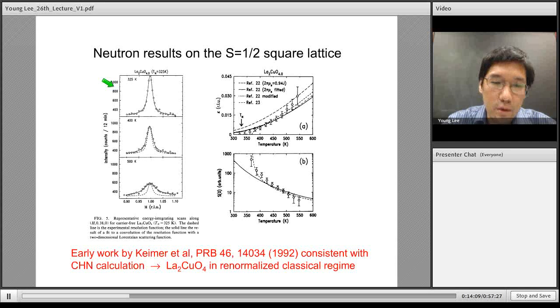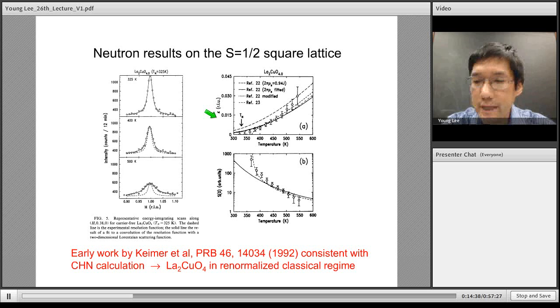When they extract the correlation length from these fits, using a simple Ornstein-Zernike Lorentzian fit, they get the following data points. So this is kappa, which is the width in Q, so this is the inverse correlation length. And they see that kappa starts to drop, meaning the correlations increase as you cool down. And clearly at T_N, it should go to 0, because that's where you have long-range order, and you should have your divergent correlation length right at that critical point.